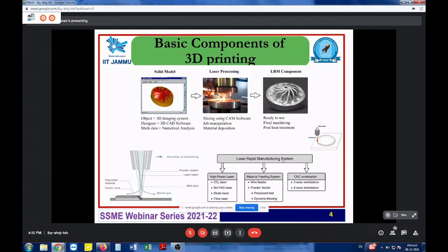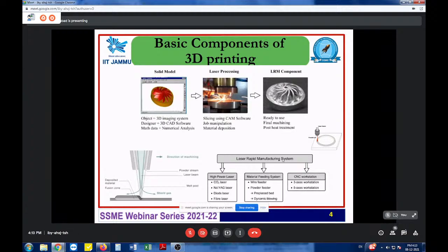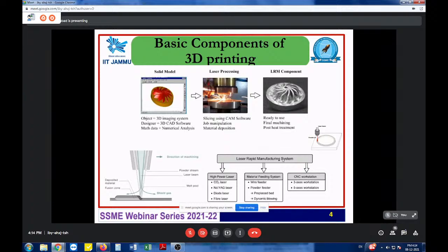In a powder-based feeder, it is trickier and requires serious effort in maintaining powder flow. Another way is dynamic blowing and a pre-placed bed. In the pre-placed bed, layer-by-layer additive manufacturing uses powder-based deposition, also known as Selective Laser Melting, where localized layers are melted out of the pre-placed powder bed. In dynamic blowing, the powder feeding is governed by a screw-based motor or carrier gas — typically argon — for a controlled atmosphere to blow the powder dynamically, as shown in the sectional view.